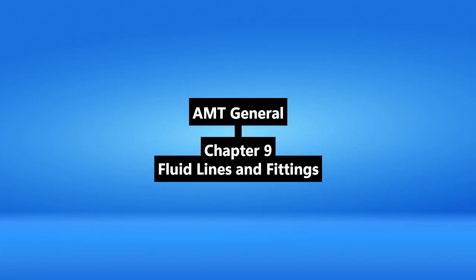Is there a limit to how much flattening is okay? There is. The smallest diameter in the bend shouldn't be less than 75% of the original OD. Okay. Figure 9-8 shows good versus bad bends: flattened, wrinkled, kinked. Those are definite no-goes. And for big production runs or really hard tubes? They mention CNC benders, like in Figure 9-9. And there are standard bend radii you need to stick to, listed in Figure 9-4. Helps maintain strength and flow.